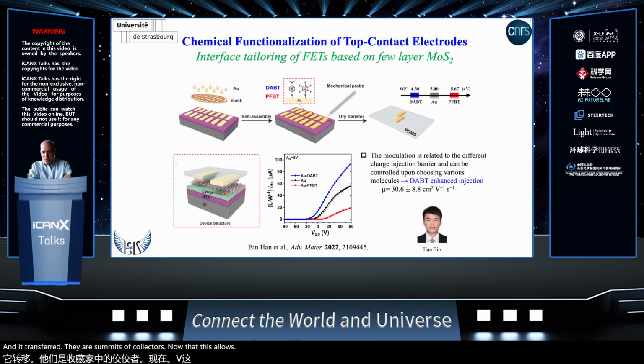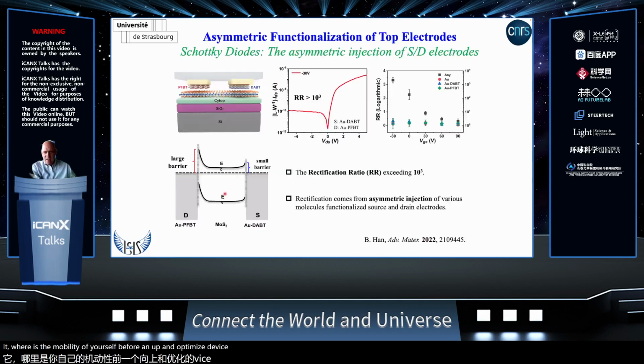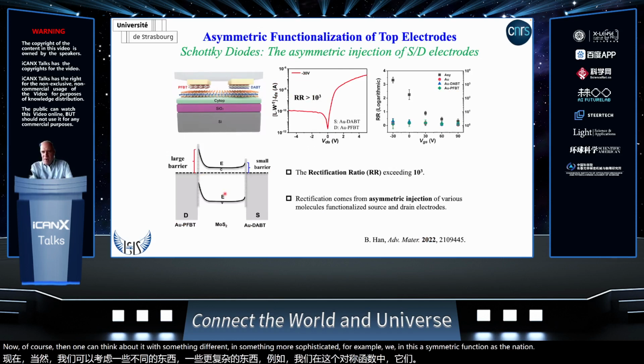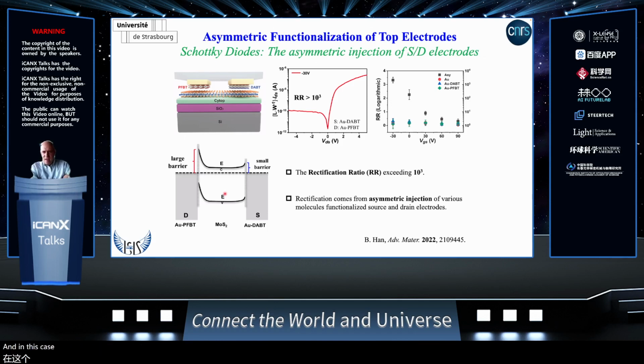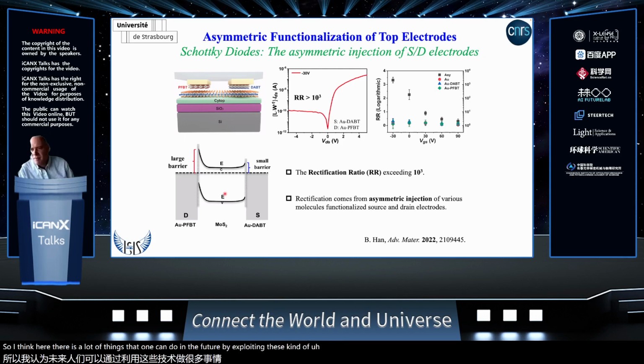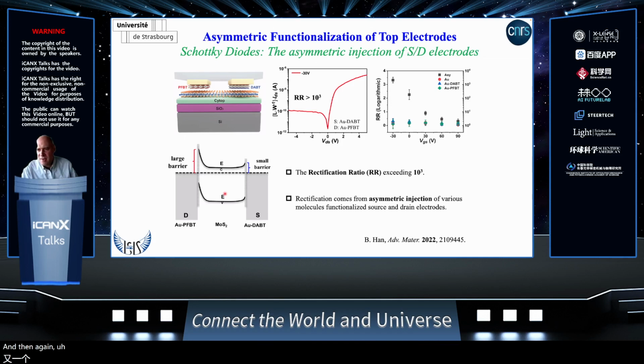Now, this allowed us to optimize the charge injection at the interface between the electrodes and the semiconductor by minimizing the injection barrier, in particular in the case we choose the DABT functionalized electrodes. And this allowed us to reach a mobility of over 30 for an optimized device. Now, of course, one can think about doing something different and something more sophisticated. For example, in this asymmetric functionalization, we could fabricate Schottky diodes. And in this case, we showed that we have a rectification ratio that can go up to 10 to the power 3. So I think here there is a lot of things that one can do in the future by exploiting this kind of asymmetric functionalization of top contacts. And again, it is really a fundamental building block for doing electronics, eventually by exploring how light can interact with matter in this kind of unique geometry.